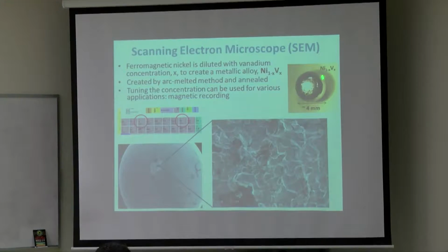And then I also annealed the sample, which means I baked it in the oven for a little bit. When I change the concentration, where X is denoted as the concentration of vanadium, there are some applications that you can utilize with this. It's been known in the past to be used for magnetic recording tapes. So it has some pretty interesting properties, but the purpose for today, I really just wanted to show you the pictures on the SEM that I used.